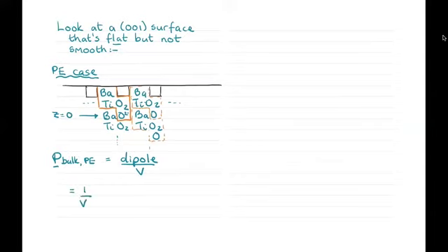And so my bulk polarization is then a charge of -2 from the oxygen times 0 for position Z equal to 0, plus a charge of 0 for the TiO2 layer, which has 0 charge, times A/2 for the position of the TiO2 layer, plus a charge of +2 for the barium, times position A, where A is the size of the conventional unit cell.